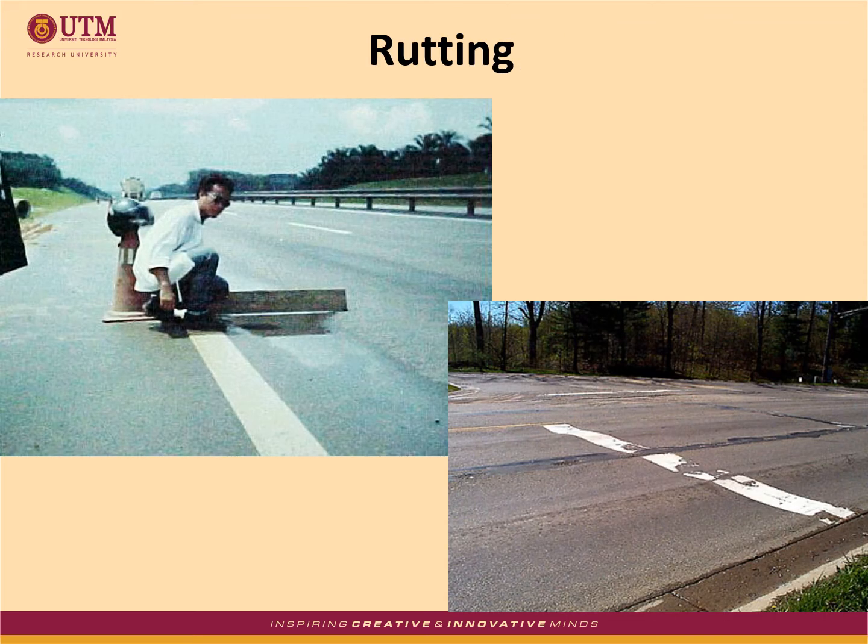Right, this is rutting. Ruts in asphalt pavements are depressions along the wheel path. It results from the consolidation or lateral movement of any of the pavement layers or subgrade under the traffic loading. It is caused by insufficient pavement thickness, lack of compaction of the asphalt, weak asphalt mixtures, or moisture infiltration. To fix the problem, if the rutting is minor, the depressions can be filled and overlaid. But if the deformations are severe, the rut area should be removed and replaced with suitable material.